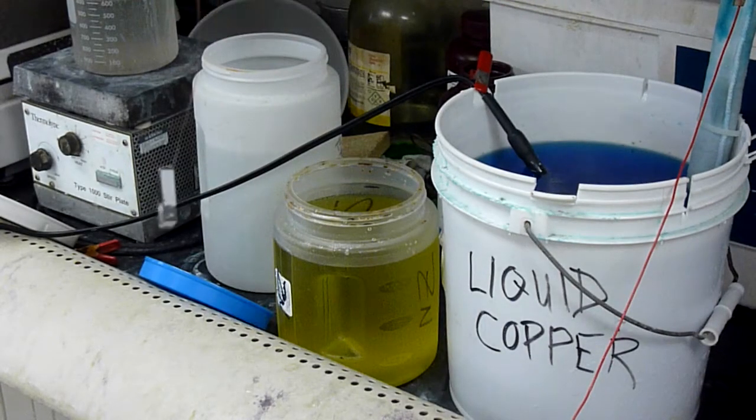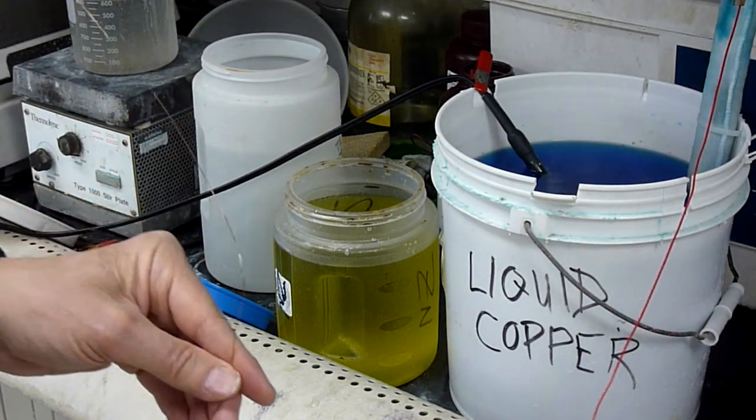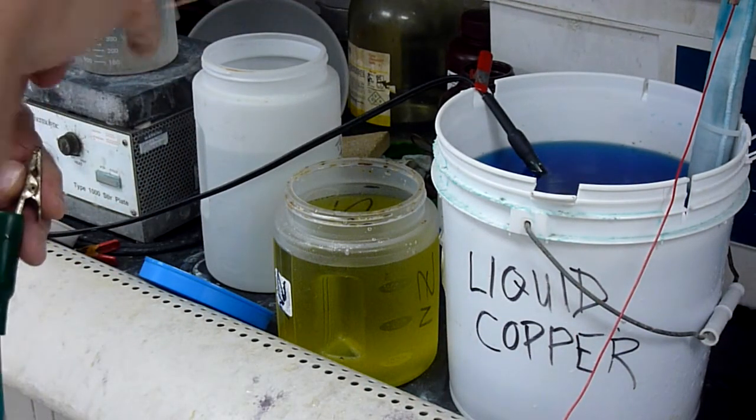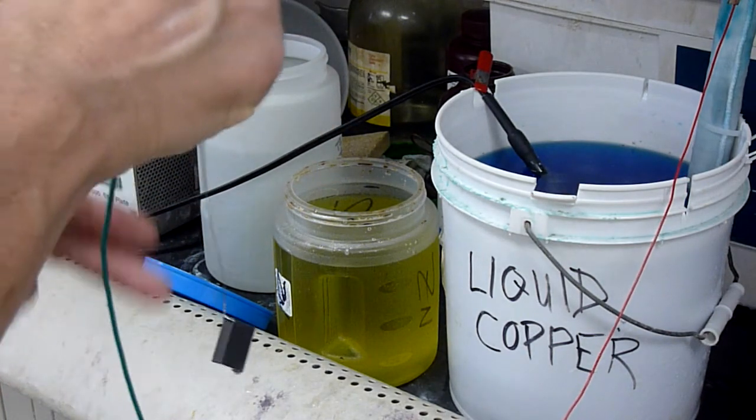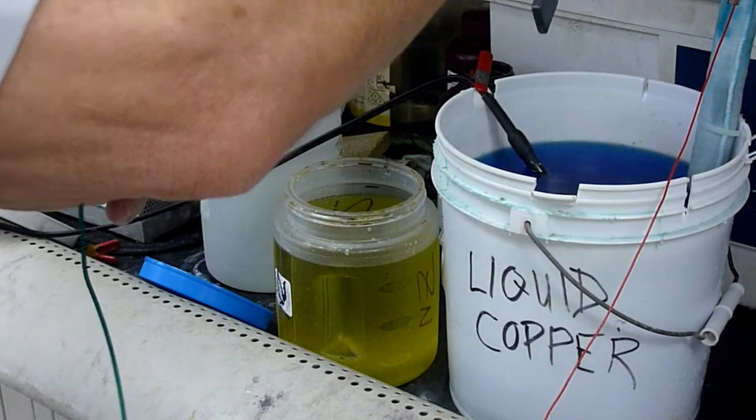I really intended to do that in this video, but let's go ahead and do our next possible plating step on this. Now in our lab here at the CDL, when you've done zincation on aluminum, your next step is either going to be copper plating with alkali copper, a Caswell product called flash copper, or we can use an electroless nickel plate, EN plate 7601. Okay, so I'm going to go into an electroplate now of alkali copper.